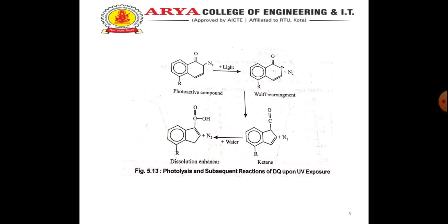You can see directly in this diagram how the nitrogen molecule N2 is weakly bonded. The addition of ultraviolet light will free the nitrogen molecule from the carbon ring, leaving behind a highly reactive carbon site. In the presence of water, a final rearrangement occurs in which the double bond to this external carbon is replaced with a single bond and an OH group. The final product is carboxylic acid.